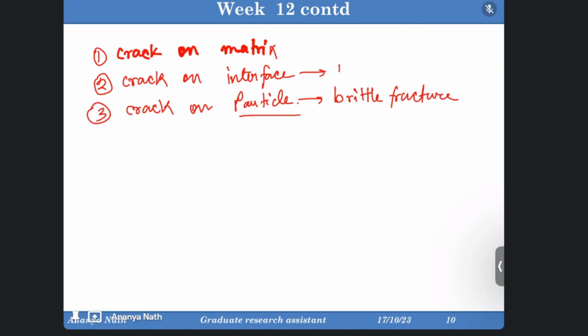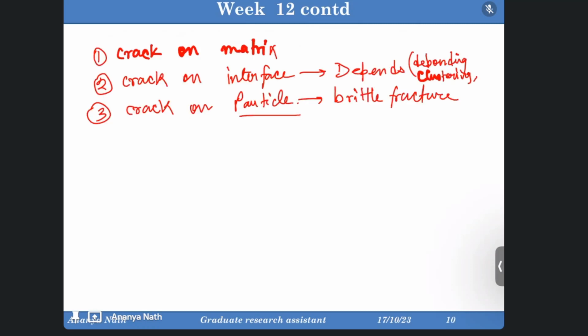If it's on the interface, it depends. It can lead to debonding, it can lead to some clustering, or some bending, or crack closure can also take place, or crack trapping or bridging can also take place if it's in the matrix. There can be bridging, trapping, closure, or it can just simply propagate through the matrix if there are no particles sitting over the movement of the crack or propagation of the crack.